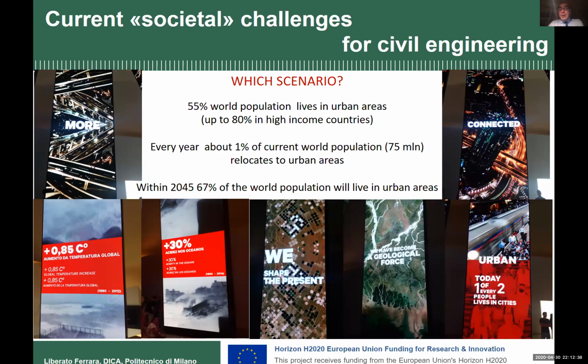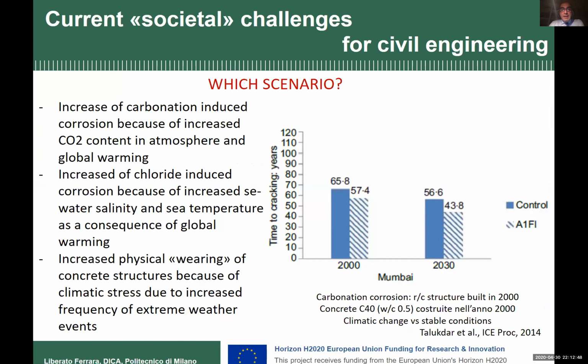And which are the consequences of this, for example, on concrete structures? Well, because of climate change, we have increase of carbonation-induced corrosion, because in our atmosphere the CO2 content increases and there is global warming, which also promotes carbonation. We have, because of increased seawater salinity and acidification and increase of sea temperature, an increase of chloride-induced corrosion. And because of extreme events, we can also have increased physical wearing of concrete structures.